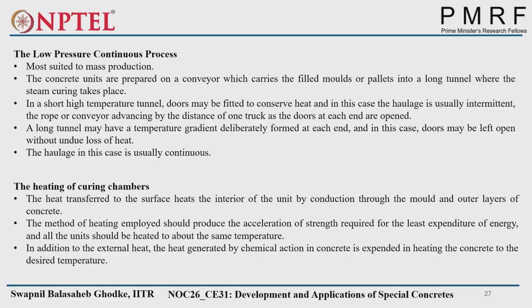Then, heating of curing chambers: the heat transferred to the surface heats the interior of the unit by conduction through the mold and outer layers of the concrete. The method of heating employed should produce the required acceleration of strength for the least expenditure of energy, and all the units should be heated to about the same temperature. In addition to the external heat, the heat generated by the chemical reaction in concrete is expended in heating the concrete to the desired temperature. So along with the exothermic reaction, that heat is also used to maintain the temperature of the curing chambers.